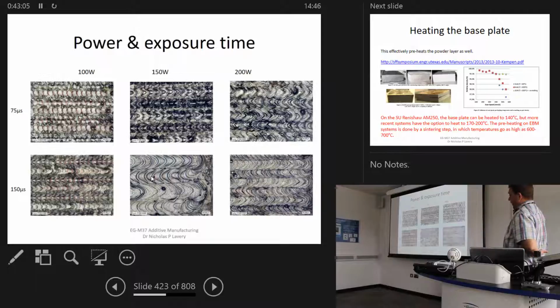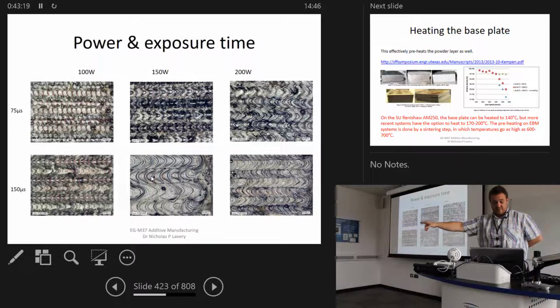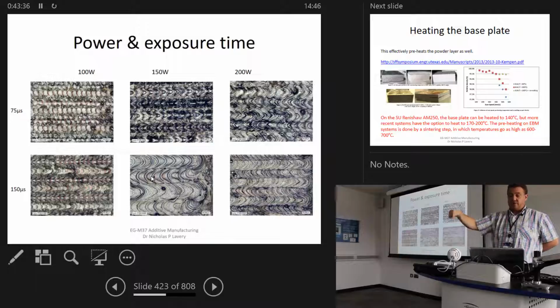Here's another example of what another experiment we might do, which is to vary the power and exposure time here between 100 watts and 200 watts, and we vary the exposure time. And you can see some interesting patterns which are left on the first layer of the melt. You can see on the first one on the left hand side there, on the short exposure time, short power, what you're getting in terms of the actual spots. You can see it's circled in red. You can actually see the individual spots of the laser as it goes along. Once you increase the power and increase the exposure time, those single spots become more blurred into what looks like a sort of line, and it's almost as if someone smeared the picture for you.